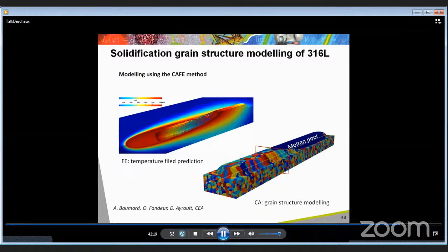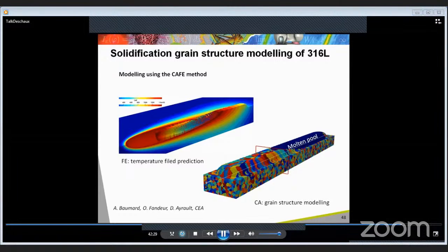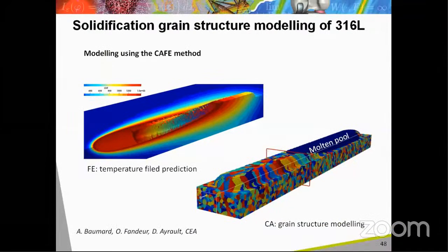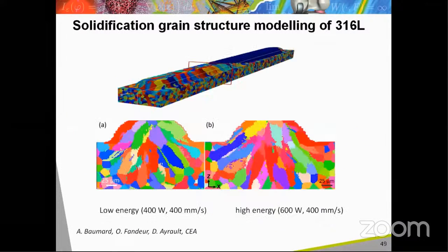For this modeling, the CAFE method is used, that couples a finite element method to predict the evolution of thermal fields during the AM process, and a cellular automata method to model the grain growth during the solidification process. One can see on this slide a comparison of cross-sections of the simulated grain structures obtained with two different process parameters corresponding to various energy levels. The grain structures are rather similar, but a slightly higher grain size is obtained when the heat energy is higher.